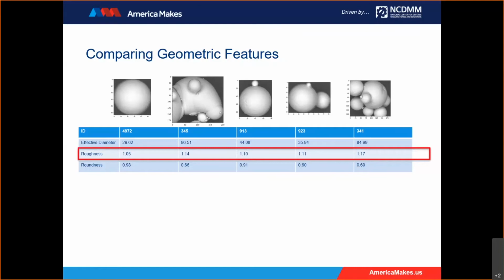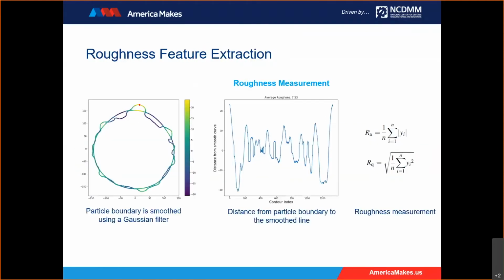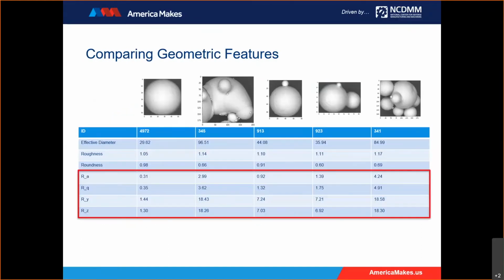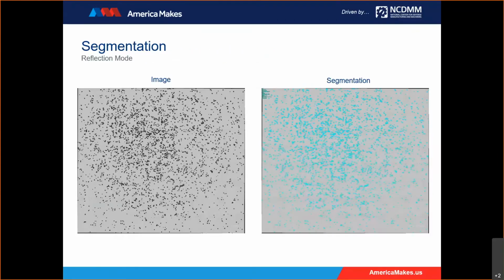So we decided to use a different approach. In this approach, we're trying to measure particle roughness in a similar way to what's typically done for surface roughness. By measuring the distance between the particle surface and the smoothed boundary, we can extract a surface roughness profile. In this way, we can get a very different measurement of roughness for the particles. If we look at the Ra, Rq, Ry, and Rz, we now have very different values that can help us classify powder into different categories.